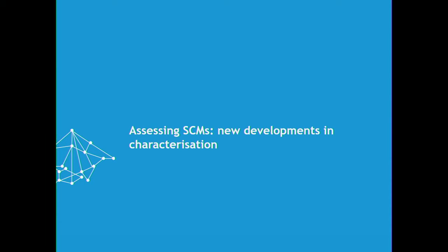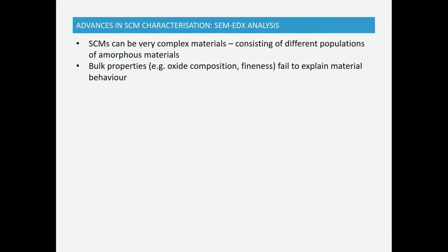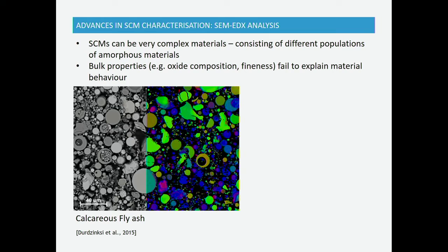Okay, so in the presentation I will showcase some of the work we have done lately. One of the nicest contributions was to progress work by SCM EDX analysis. I was lucky to be able to contribute to that, but much of this has been developed with my colleagues at EPFL. As SCMs can be very complex materials, this is a picture, for instance, of calcareous fly ash, where you can see a normal BSE picture here. And this is the same picture, but with the element mappings of silicon, aluminum, and calcium superimposed. So calcium is blue, silicon is green, and aluminum is the reddish color. And you can really see there are very different populations in composition of particles.